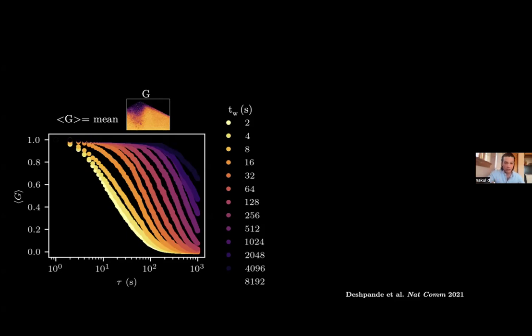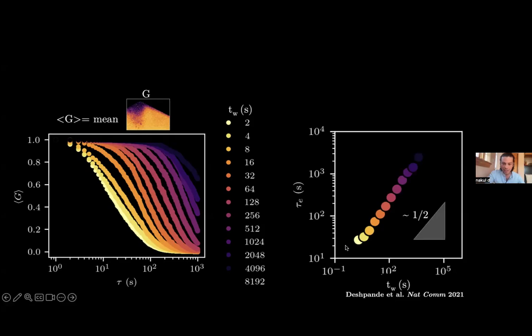We can quantify this slowing down by extracting our relaxation time for each one of these curves. And you can see that the time that it takes for this pile to relax grows as approximately a power law with time, okay? So my pile gets slower and slower, it creeps slower and slower, and the way in which it creeps slower and slower is a power law with time. So we've repeated this experiment many times. I don't hang my hat on the 1/2 power law. All of them are less than one though. So there's nothing necessarily universal about this other than this less than one relaxation.